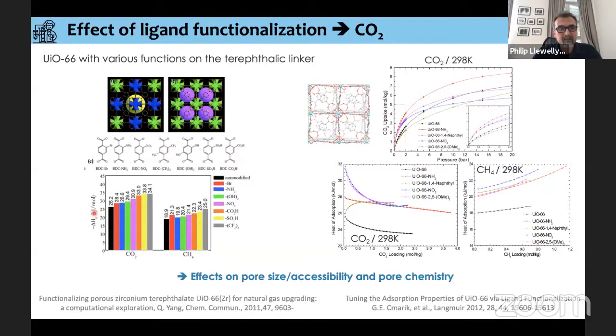They carried out a screening and looked at the interaction, via the enthalpy of adsorption, for CO2 and methane here. We can see that both actually change with respect to the different linkers. What they then did is validate some of these data with direct calorimetry experiments, which we carried out in Marseille. Similar types of results have been obtained in a second study, and again we have the isotherms for CO2 here, and then the enthalpies of adsorption as a function of loading for methane here and CO2 here.